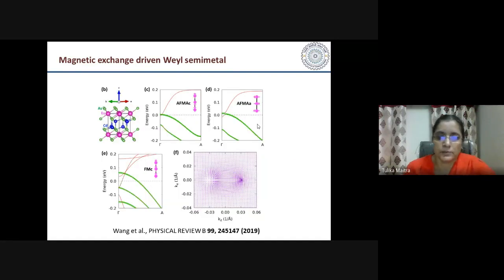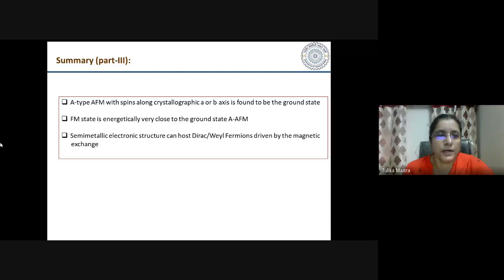And then later on, detailed electronic structure calculations were done by Wang and others, where they looked at various magnetic states we had considered, and they calculated the chirality of these Weyl points, and they found that indeed there is a pair of Weyl points at the Fermi level in the ferromagnetic state. Okay. So let me then summarize this part. The A-type antiferromagnetic state with spins along the crystallographic A or B axis is found to be the ground state. And the FM state, the ferromagnetic state, is found to be energetically very close to the ground state, which is A-type antiferromagnetic. And the semi-metallic electronic structure can host Dirac or Weyl fermions driven by magnetic exchange. This is what we have found from our calculations.